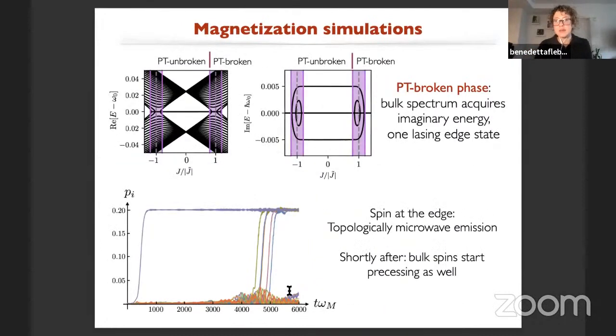Is this related to the topological phase? Well, it seems to be definitely related, because when we move far away from there, so for example, we start moving here, we can see in our simulation that the lasing edge state, the spin that corresponds to that growing magnon population, starts precessing first. But then after a while, all the other spins will also start precessing, and these are really the spins associated with the bulk modes that become degenerate with the edge states. So the signal that we expect is very different. And I don't think I reported it here, but if you start really moving further into this region, you would see that all the bulk and edge states start precessing exactly as you would expect from a classical standpoint.